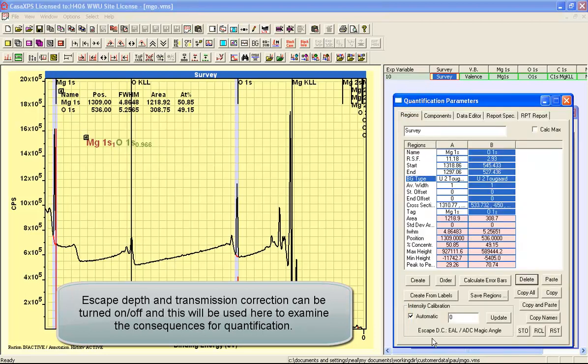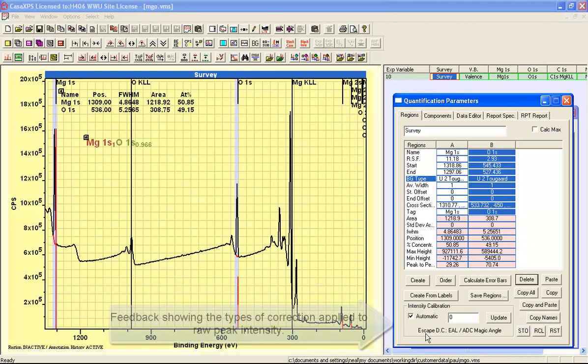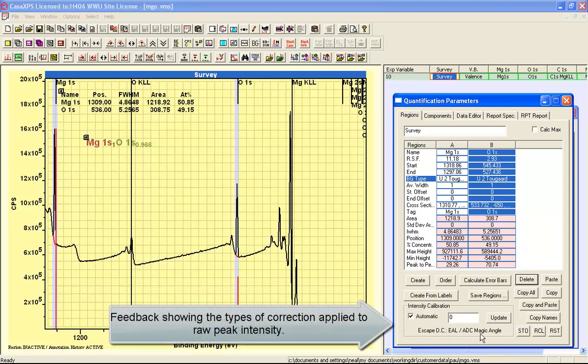On the regions property page, the indication at the bottom here is that we've used a magic angle instrument. Actually, they're both S orbitals, so it really doesn't matter whether it's a magic angle instrument or not. S orbitals will always have the same relationship. It's only when you have P, D, F does it make a difference if you have a non-magic angle instrument.